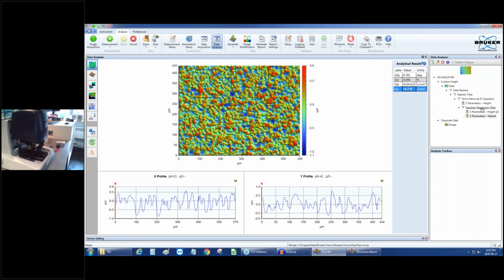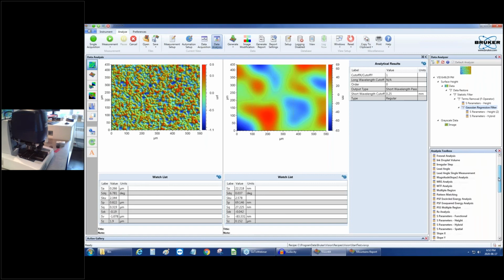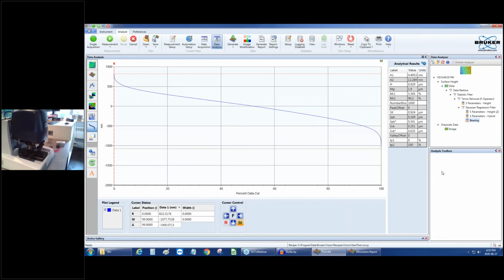There was a question regarding what would make sense in terms of parameters regarding sealing surfaces. And in that case, what we will mobilize is certainly the bearing information, so with the Abbott curve, because parameters such as the SPK will definitely be important, telling what is the height of the peaks on average facing the surface. So this Abbott curve tells how the surface sustains the pressures and how many of the points are in contact. So the flatter this bearing curve is, the better in terms of sustaining the pressure across all the surface. The more you have, let's say, an S-shaped curve, the more you will have leakage through the lowest point. So the SVK will be important, as much as some information about the volumes of the valleys, which is more about A1 and A2.